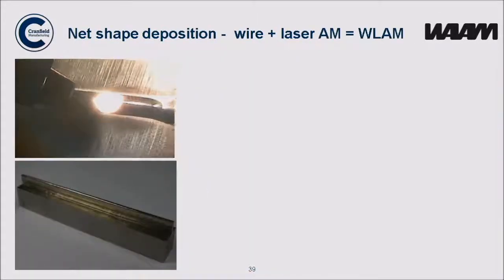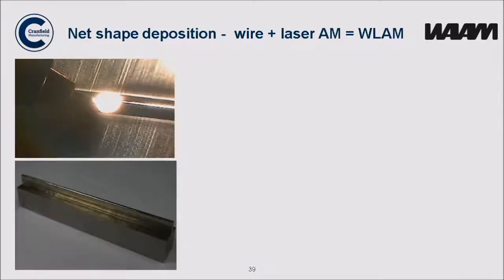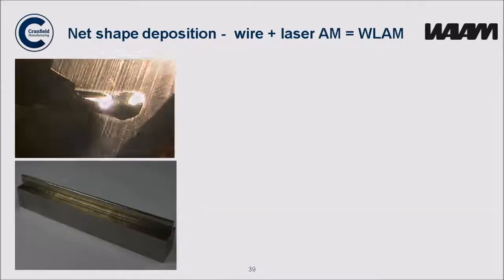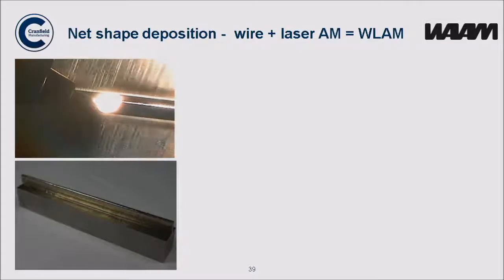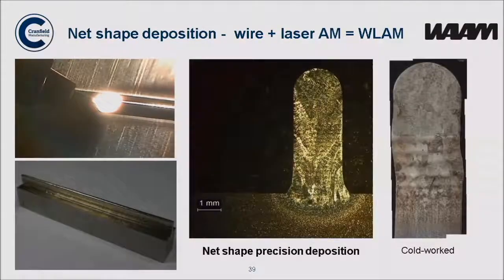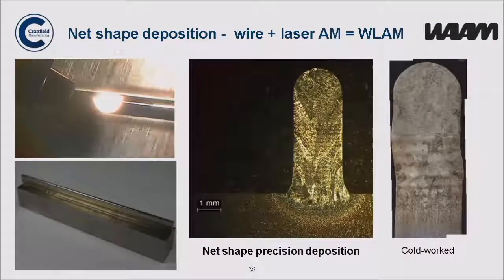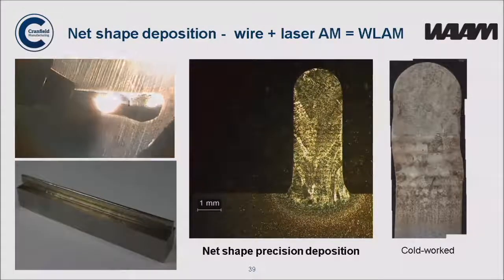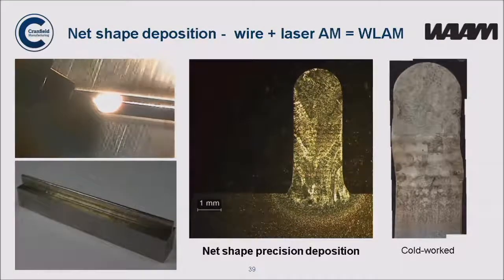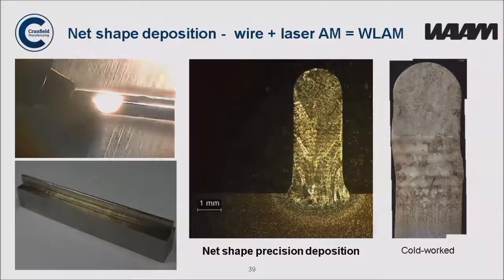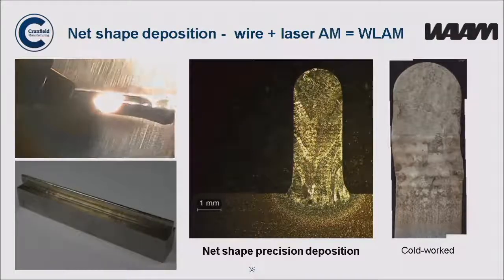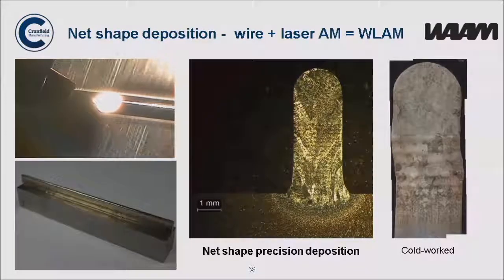At the other end, if we take the wire and laser approach, so here you can see wire and laser deposition. And in fact, using wire and laser, you can get down to feature sizes just the same as laser powder, as long as you know how to control the wire properly. And you can see underneath a simple part. And if you look at a cross-section of this, you can see we get net shape deposition. So there are no surface waviness features. As long as you get the width correct, there is no requirement to machine it. And in this case as well, on the picture on the right, you can see we actually cold work this using peening, and by using that method, we're able to eliminate the large prior beta grains.